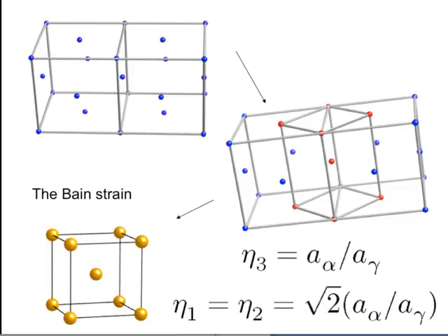But you can see that if I now compress it along the vertical axis and uniformly expand it along the horizontal axis, I can change that into a cube, right? So that is called the Bain strain, where you have a deformation this way and a uniform expansion along the x and y axis, and you generate your cubic, body-centered cubic structure. It's really a very beautiful